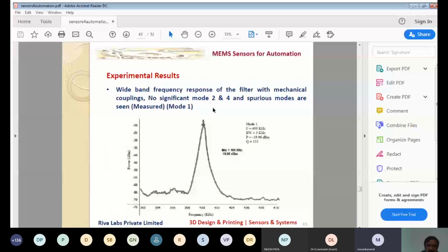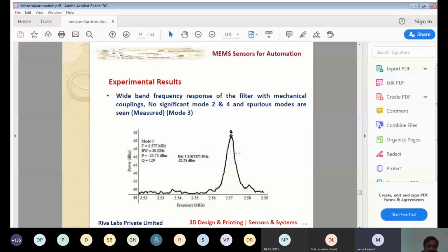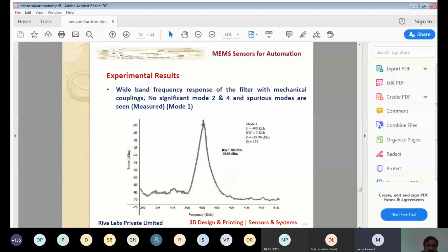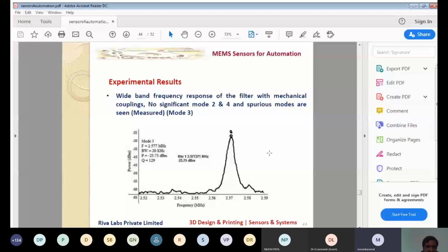This is the output which we plotted using a network analyzer. On the network analyzer you have the frequency response, which shows you the output power in dBm. It tells you the frequency, the bandwidth, the power, and also the Q. This is the mode 1 response which was measured, and this is the mode 3 response which was measured. So we demonstrated the operation of mode 1 and mode 3 in a single device. This is dual band operation where all other bands were suppressed. We got the output only at the 2 different bands.